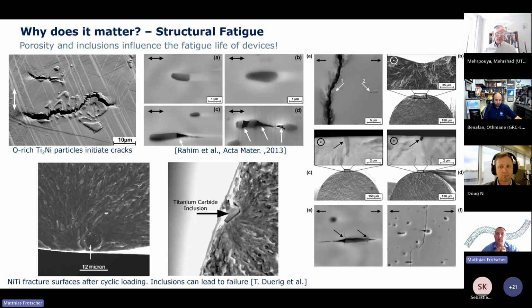Inclusions can also form what is called particle void assemblies, or PVAs in literature. They form during deformation of nitinol material, for example, when manufacturing wires or tubing, and the nitinol matrix is deformed, but the hard and brittle secondary phases break up during this process and are elongated, forming stringers in the forming direction. And in some cases, the nitinol matrix is not fully closed around the inclusions after processing, leaving these porosities close to the particles. And at the interface between the porosity and the inclusions is the highest stress location where the crack would initiate. And those cracks can connect, allowing the crack to more easily propagate through the material from one inclusion to the other.